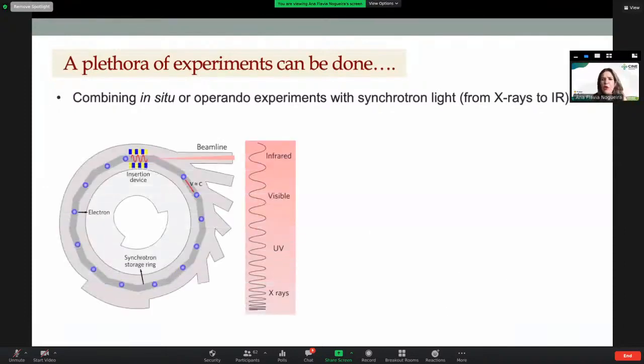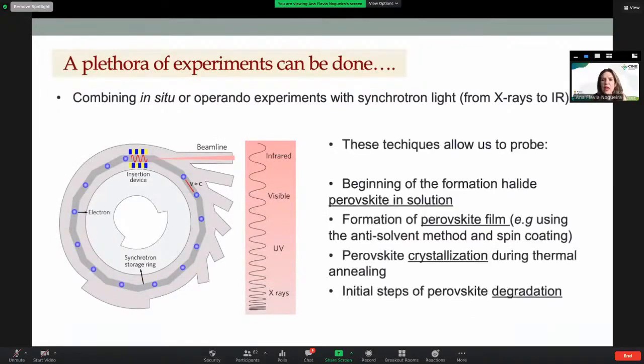And we're going to show you today that for the perovskite materials, when you couple the synchrotron radiation with these in situ experiments, we can track the beginning of the formation of the halide perovskite in solution. Okay, you can make a reaction in a beamline. Also, we can follow the formation of the perovskite film and compare the methods to prepare this film. And also we can follow what happens with the perovskites during the thermal annealing. That's a really important step. And also we can probe the initial steps of the degradation. I'm going to show you two types of results, because of the time,